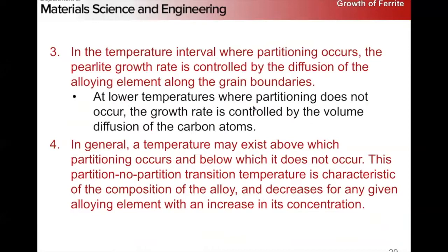Unless we're at lower temperatures, partitioning doesn't occur, then our growth rate is going to be controlled by the volume diffusion of the carbon atoms, right? So if we're at lower temperatures or high supersaturation of carbons, carbon controls the growth rate. If we're at high temperatures, where we have less of a driving force for transformation, our rate is going to be governed by how fast our solute atoms can partition.